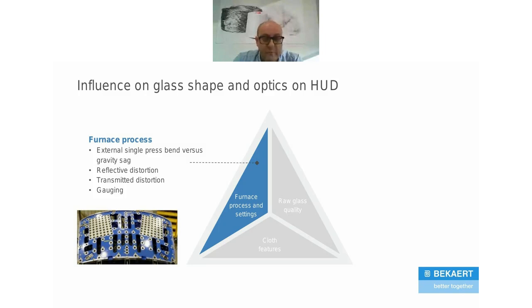So these are quite important things on a glass to have the best optical quality in your glass. This is typically a picture that you can see for a head-up display, where you have a measurement system with a lot of points that are measuring the height of the glass. This is typically what you see to measure gauging for a head-up display glass.